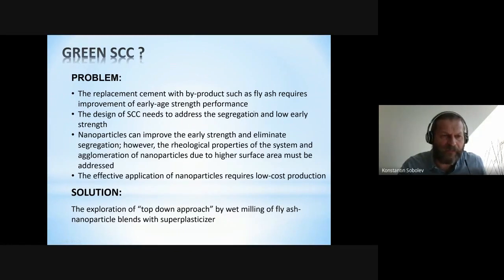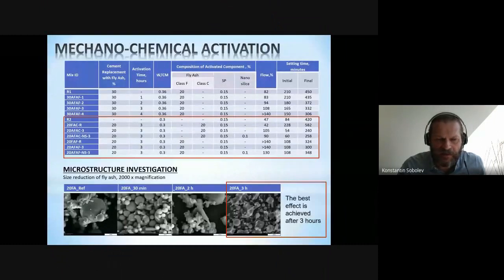Can we do better? Can we produce green self-consolidating concrete and try to use class F fly ash as a precursor? Obviously, wet milling of fly ash nanoparticle blends with superplasticizer can be realized. And we ran a preliminary experiment with Class F fly ash for 3 hours. And you can see that you can really have effective wet milling and strength improvement with class F fly ash